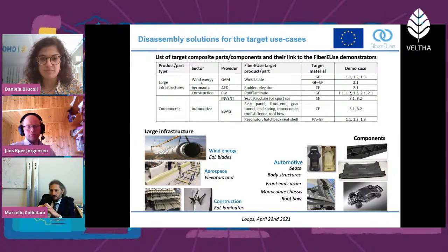But of course, to get there, you need to carefully evaluate the concentration of the fibers in the input components. And I tell you, in blades, it is not homogeneous. If you take a part of the blade close to the rotor, the concentration of fiber is completely different from a part of the blade that is far from the rotor and close to the edge. So if you want to reuse this material, you really need to start from the demand of the reusers, of the products that embed the reusable material, and pool the demand and adapt your process in order to obtain a stable fractional material meeting those requirements.